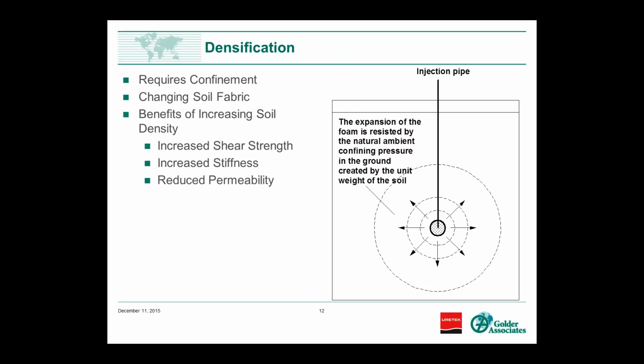And the densification is one of the really unique aspects of URETEK's deep injection process, in that you can actually have some densification of the soil. For that to happen, though, you need confinement. Once some of the voids have been filled, the cracks and fissures in the soil formation have been filled up, and you've started to seal things up a little bit, that's when you start seeing the density improvements.